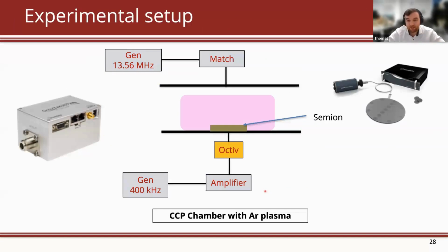So this is the experimental setup. It's almost time for the demo. So we have a capacitively coupled chamber. We have a 13.56 megahertz on top through a match to make the plasma. And then we have a signal generator, which we're using 400 kilohertz as our base frequency. We have an amplifier. And then after the amplifier, we have an Octiv, and this Octiv is just below the electrode. So we have an Octiv suite. And the Octiv suite is going to show you what the waveform shape is. So we can directly measure what the waveform shape is and measure what the voltage is during the experiments. And then in the chamber, we have a Semion system, which is going to measure the ion energy distribution function. And we're just using an argon plasma CCP chamber.